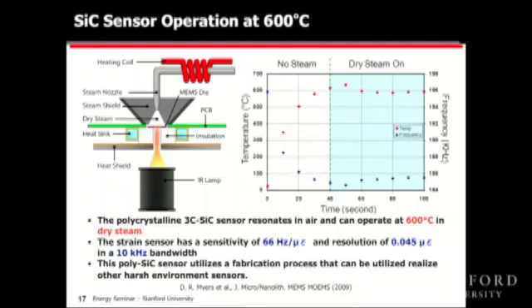This is the temperature ramp here, the red dots going from room temperature up to 600 degrees C. And we can see the blue dots here denoting the frequency at which this sensing structure is resonating. What you can see here is once we hit 600 degrees C, the device continues to resonate. So this is a microscale device made of silicon carbide resonating at 600 degrees C. So, a functioning electronic device at a very, very high temperature.